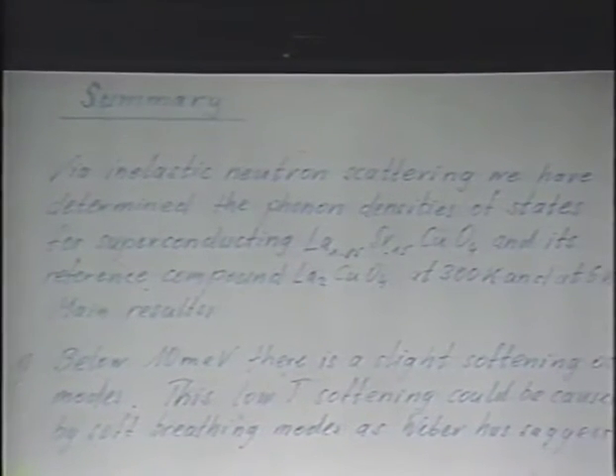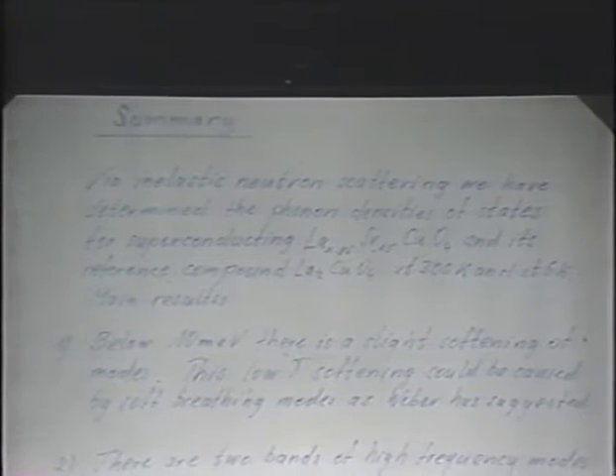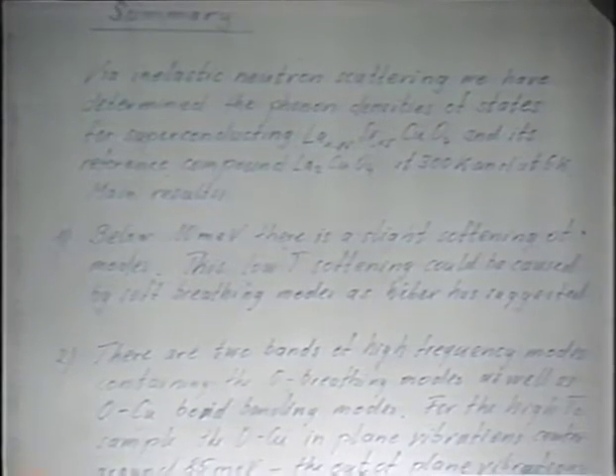So if the bell hasn't rung, I will put the summary up. Okay, via inelastic neutron scattering, we have determined the phonon densities of states for the superconductor and its reference compound, the non-superconductor La2CuO4, at 300K and at 6K. Main results: below 10 meV, there's a slight softening of modes for the superconductor. This low TC softening could be caused by soft breathing modes, as Weber has suggested.